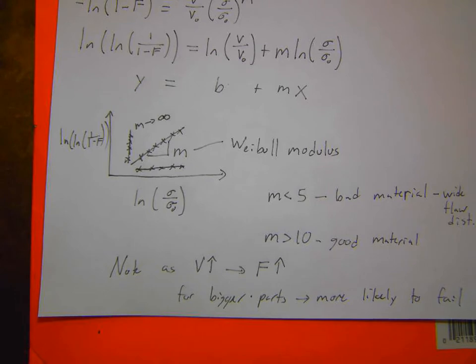But Wolfram has a demonstration project where they take some common engineering materials and look at that probability distribution. So this is the F versus sigma, the probability of failure versus the stress. And they have a little slider module where you can change the m and the critical stress value, sigma naught, the average failure strength of the material, to see how good or how bad a material is. So if I click on silicon nitride, it pulls up some actual silicon nitride data.